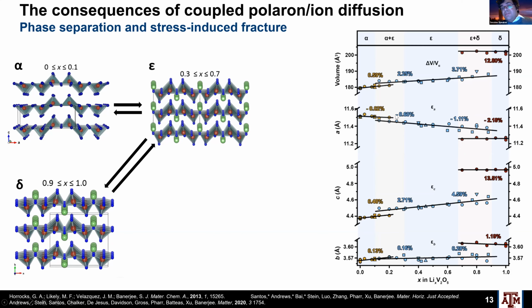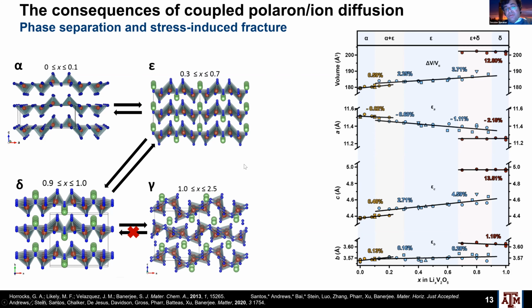regimes, phase coexistence regimes, where you will have windows of alpha plus epsilon or epsilon plus delta, and so on and so forth. And this phase coexistence has lots of implications, both in terms of the kinetics of the system, in creating these phase boundaries between differently lithiated phases that serve to block lithium ion diffusion or to create impediments to lithium ion diffusion, as well as for generating mechanical stresses as a result of the lattice mismatch at these interfaces. And so once you get to gamma, then this transformation is generally irreversible, and that then also creates a whole other set of problems.